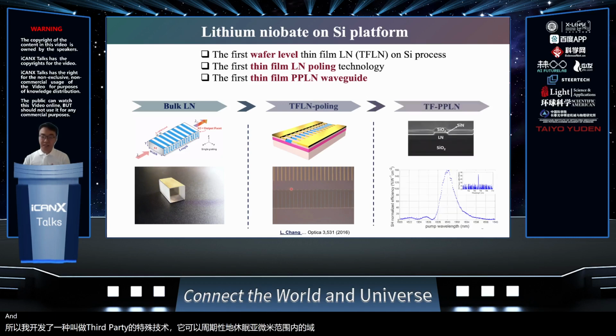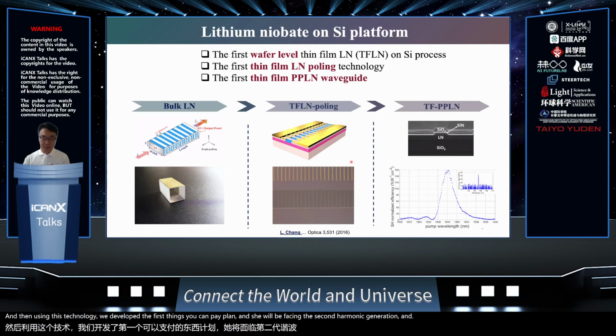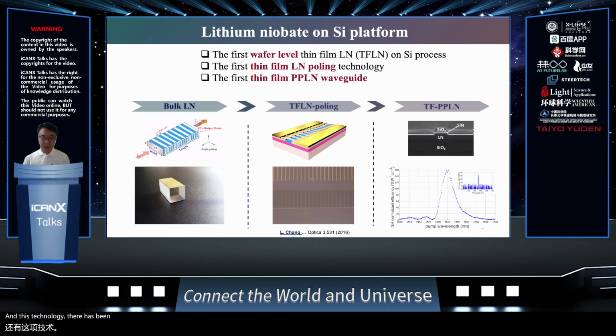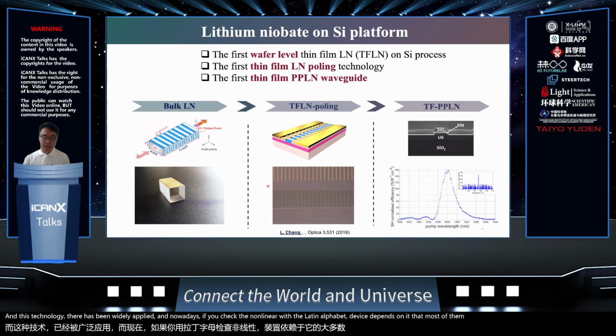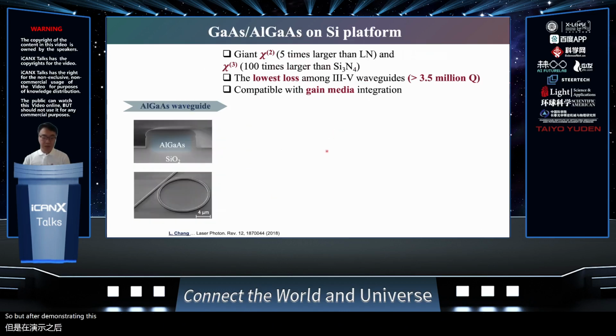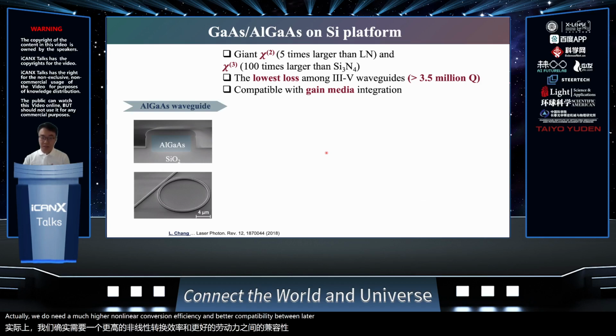Using this technology, we developed the first thin film periodically poled waveguide and achieved efficient second harmonic generation on chip. This technology has then been widely applied, and nowadays if you check the nonlinear lithium niobate devices, you can find that most of them use this kind of technology. But after demonstrating this platform, we started to realize that for many applications, we do need a much higher nonlinear conversion efficiency and better compatibility between the laser and the nonlinear device.